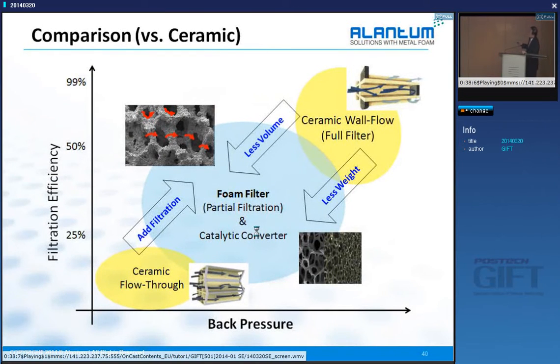If you go to the ceramic filter, there are two ways, the so-called wall flow. It goes into the tunnel, the channel, and then passes through the wall. Once you operate this, it shows nearly 99% filtration efficiency. But because of this, back pressure will dramatically increase, okay? Compared to this, a partial filter, just in a channel, has very low filtration efficiency, but fairly good, low back pressure. Our metal foam covers just in between. Our metal foam cannot make 99% filtration efficiency at all. We can make up to 80%, okay? So this is a much wider area which automotive or engine OEMs need, okay?